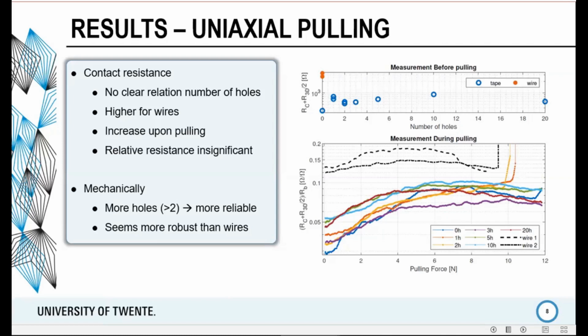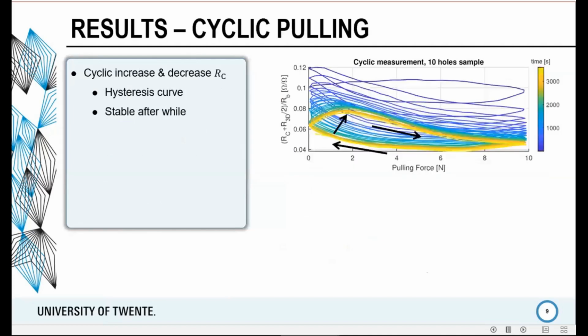So mechanically, for more than 2 holes in our design, it seemed to be quite reliable and also more robust than the wires. And what's interesting is that these materials have a really high resistivity. So actually, our contact resistance, when you put it in percentages, was insignificant compared to the total sample sensor resistance. For the cyclic measurements, you could see that after a while, a stable hysteretic cycle formed.